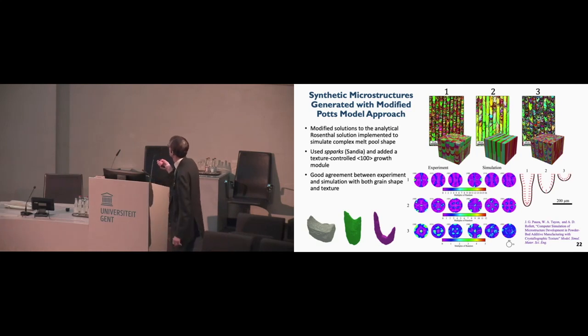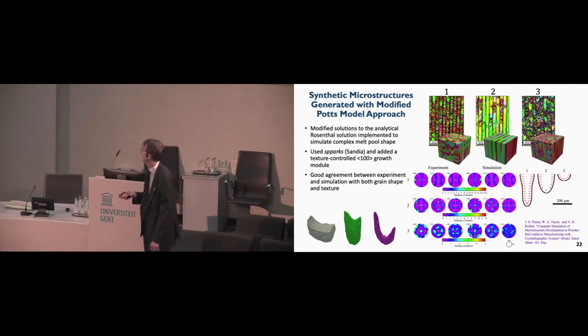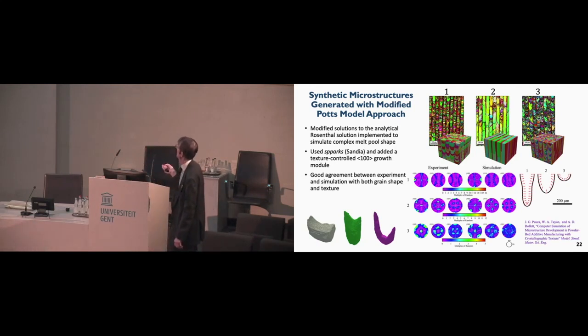And you can see also a comparison of textures, so the experimental textures in this block on the left, and then the simulated textures in the block on the right. Again, I don't have time to explain them properly, but you should ask me, well, why are they such different microstructures? And the reason is that by varying the speed in that fashion, we went from a very strong keyhole, and I will say a lot more about keyholes, to a deep melt pool, to essentially a conduction melt pool.